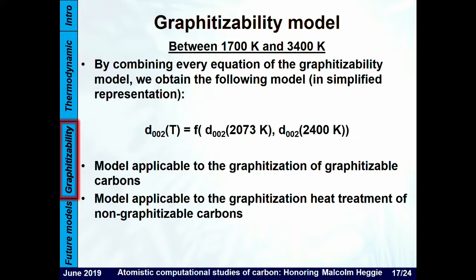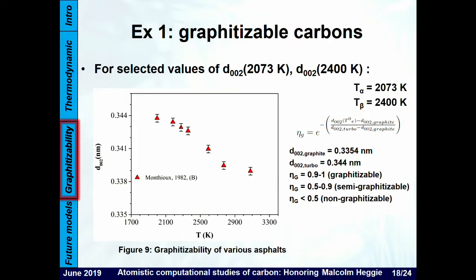So at the end of the day, you take all these equations and combine them together, and what you get is a model which allows you to calculate the D002 of graphitizable and non-graphitizable carbon simply as a function of the D002 at 2070 Kelvin and the D002 at 2400 Kelvin. The difference between these two values will give you the intensity of the graphitization, which is implicitly used to calculate the activation energy of the ATDs, and a singular value will give you more or less the average disorder in the structure. So now you can apply it to experimental results.